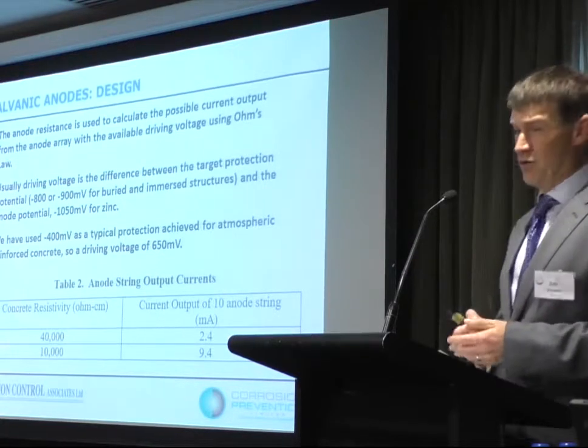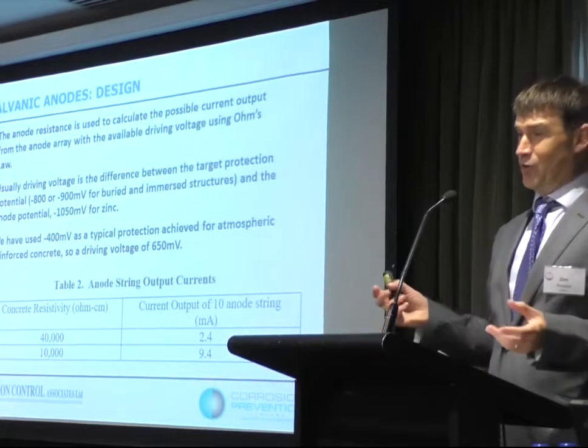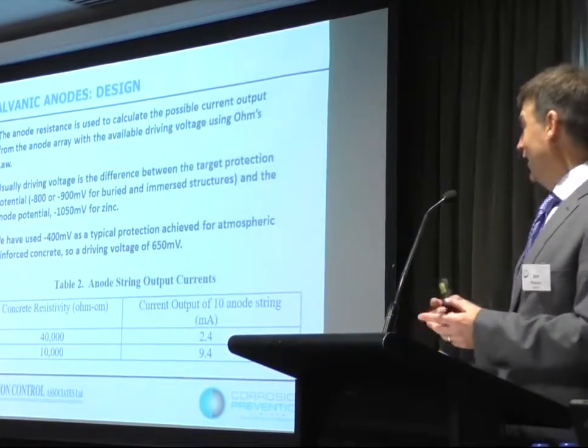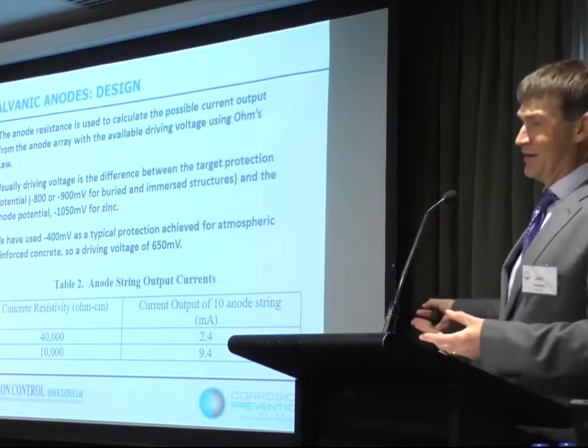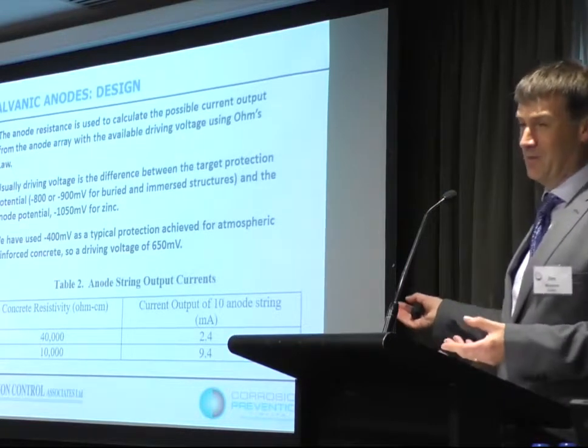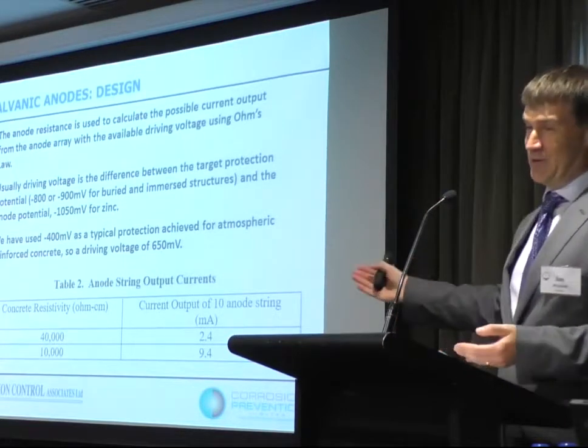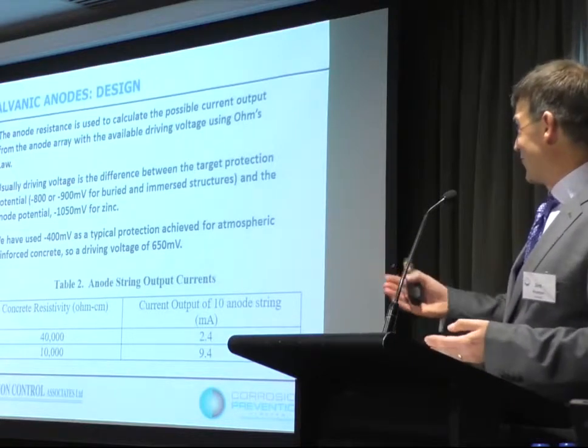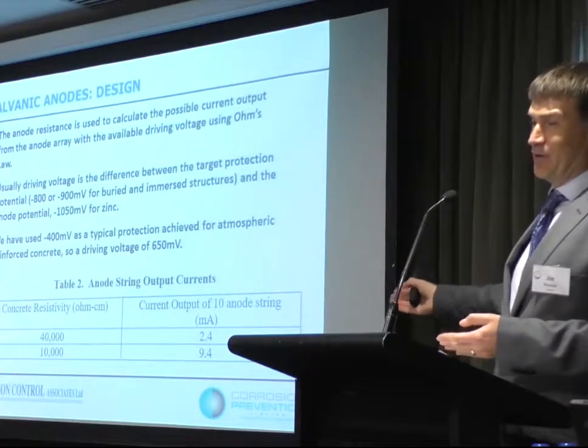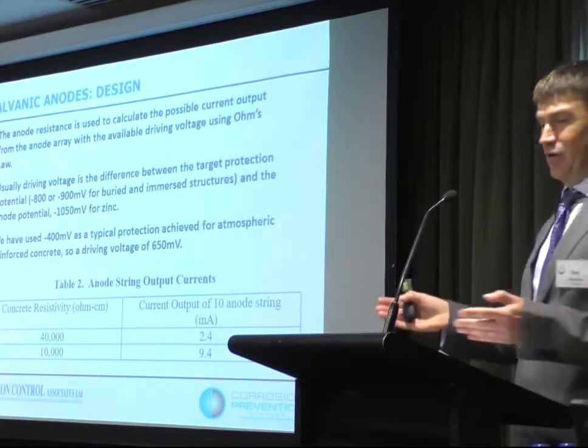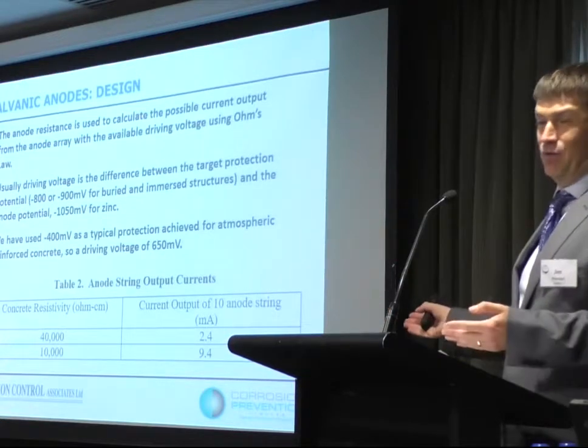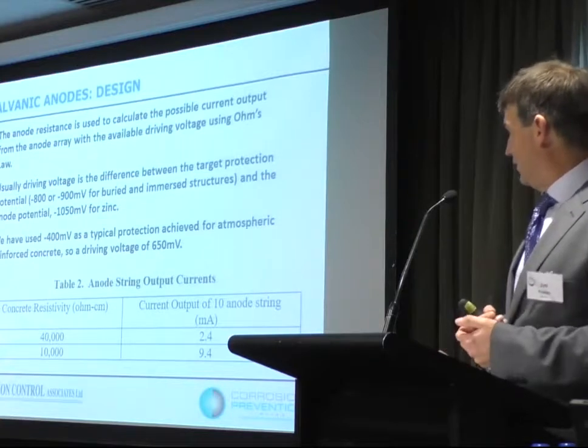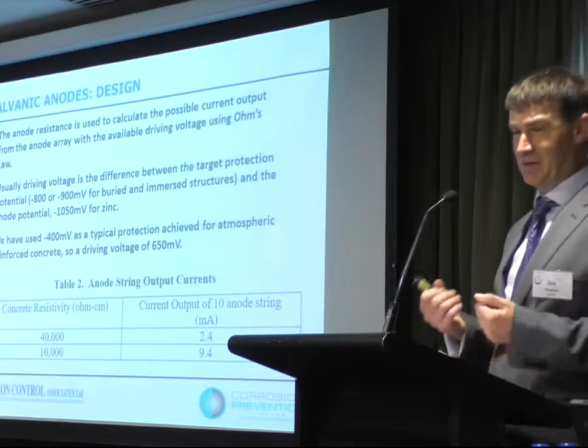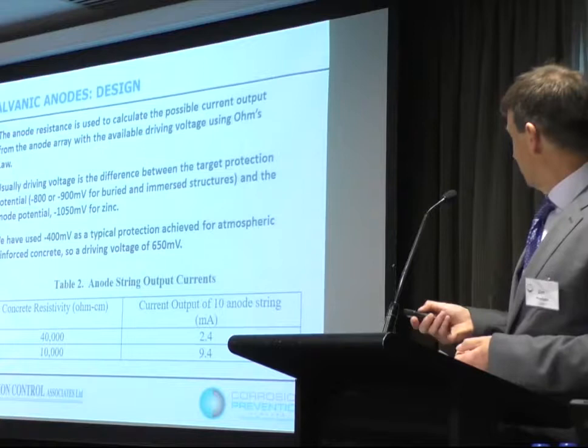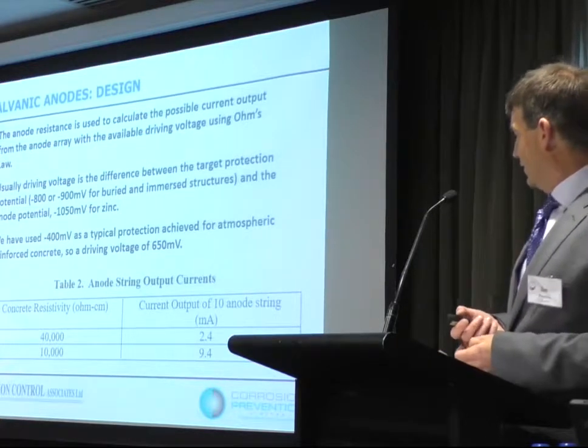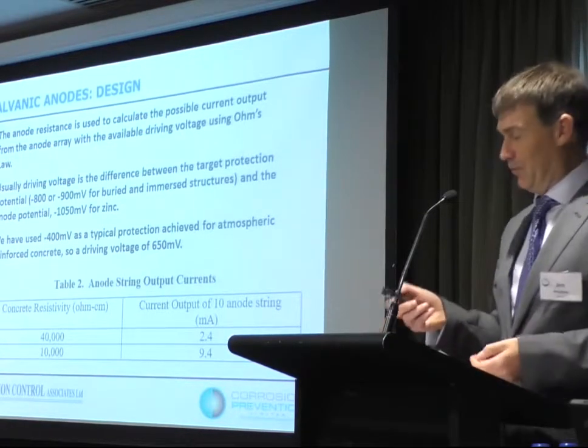We have to determine what the driving voltage is. Normally that's simple because it's the difference between our protection potential and the potential of our zinc in seawater, so it might be 150 millivolts. Now, we're not expecting to protect reinforcement in concrete up to something like -900 millivolts, but if it's corroding, we might want to shift it 100 millivolts. So let's say we're trying to get it to -400 millivolts. That gives us a 650 millivolt driving voltage, so we're giving these anodes a fighting chance. Obviously, if we've got a higher resistivity, we get less output.